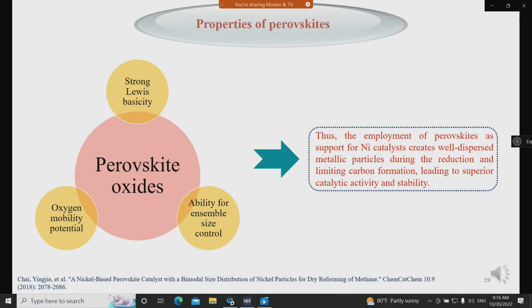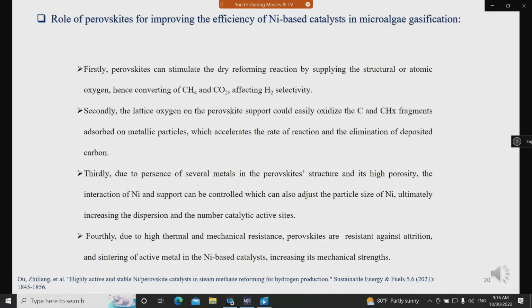So, the employment of perovskite as support for nickel catalyst creates well-dispersed metallic particles during the reduction and limits carbon formation, leading to superior catalytic activity and stability. The role of perovskite for improving the efficiency of nickel-based catalyst in microalgae gasification is as follows.